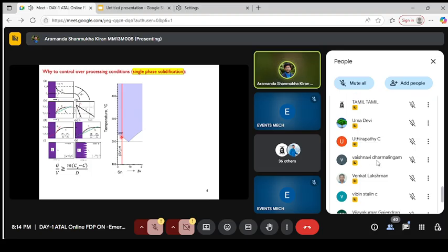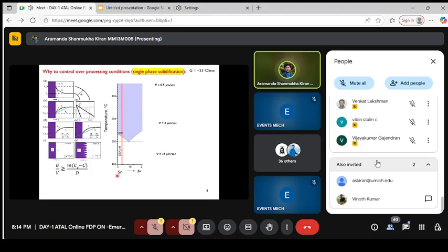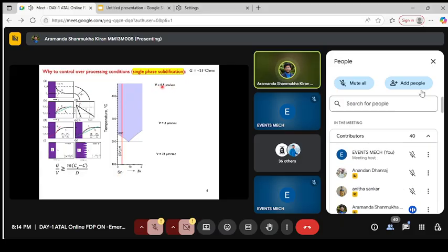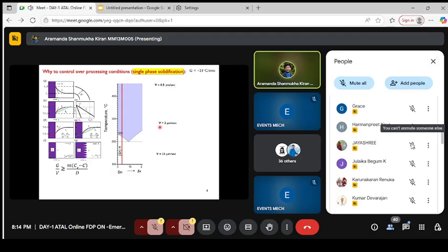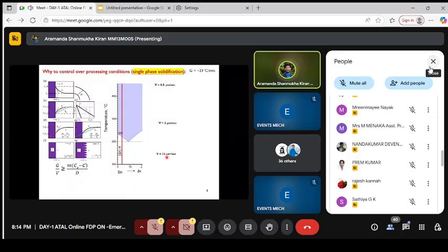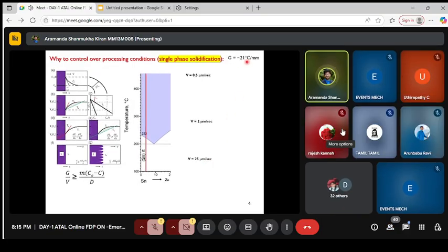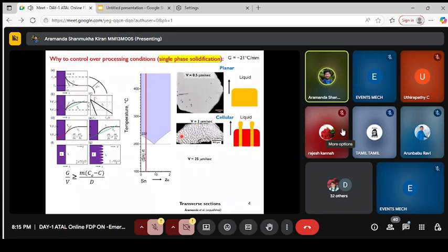But what I want to say is this alloy is taken with 4% of zinc in the tin alloy, and it is cooled at a very slow rate, like 0.5 micrometer per second, and a little faster, 2 micrometer per second, and very fast, 25 micrometer per second, with one gradient of 21 Celsius per millimeter. In the first case, when we see in the microscope, we see a single full block like this, which I am just showing as a schematic, where the single phase is coming from the liquid this way. But when it is cooled with very high speed, the microstructure in the microscope shows something like this yellow thing, which is cut in cross section. That's why it looks like this. These are all cross section images where you can see so many circular features here.